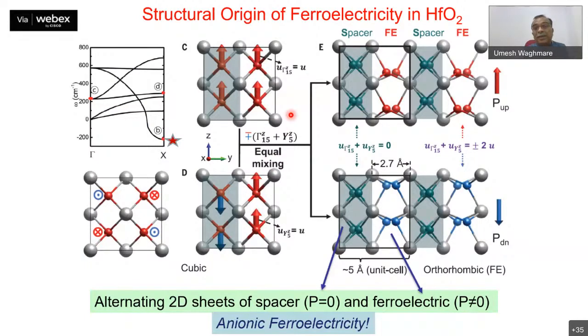But the magical thing about hafnium oxide is that both sets of displacement are equally mixed together to give you the ferroelectric wave. As a result, in half of the oxygen atoms you get zero displacement. It's a large dipole moment called the ferroelectric effect. So this is a three-dimensional architecture of hafnium oxide, which allows you to have two-dimensional electric dipole sheets, which are confined within 0.27 nanometers. You know, that's amazing. And it's purely anionic ferroelectricity, a novel type of ferroelectricity.